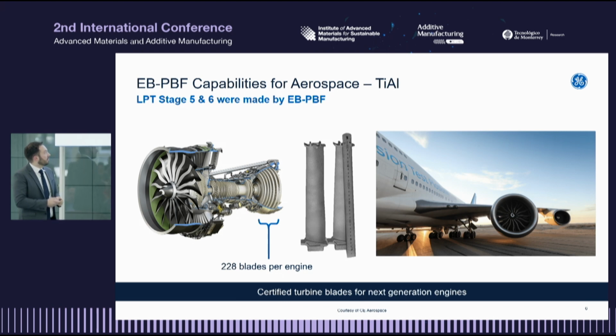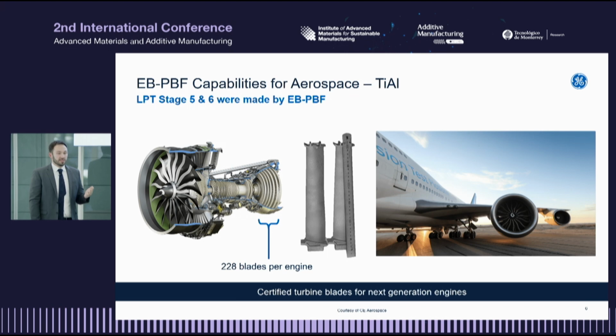And the last one that I want to mention is another EBM part, but it is in the engine, and it does have kinetic energy behind it. This part rotates. This is made of titanium aluminide, which is an intermetallic material with something like 0.5% ductility at room temperature. It is a low-pressure turbine blade, so it sits after the combustor, so I have very hot gases passing by this. But if you've been listening carefully, I've said the word titanium and aluminum next to each other. I took a relatively low temperature-capable material in titanium, added aluminum to it, which is even lower, and somehow I have a rotating part come out the back end.